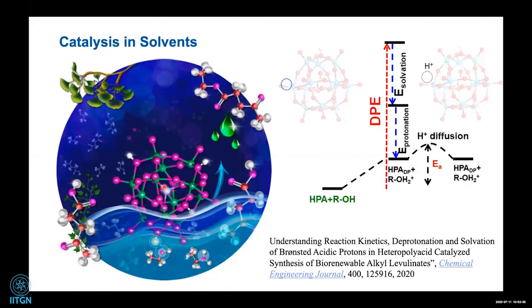The deprotonation energy — how the solvent stabilizes protons that are deprotonating in the catalysis — and the shuttling of protons are really important. Solvation and protonation determines the activation barriers seen experimentally, and that holds the key idea of engineering catalyst surfaces for designing reactions in complex reaction environments, especially for biorenewable catalysis.